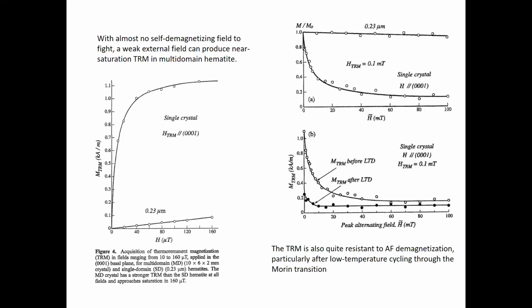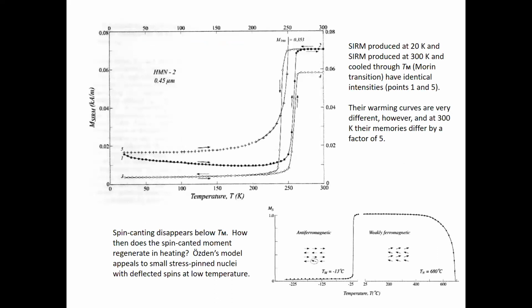And although the AF stability is not as large as single domain hematite, or else you wouldn't be able to demagnetize it at all, it's pretty respectable, and particularly after you've cycled through the Morin transition, which is the lowermost curve. This is more complex work. Özden got into a lot of experimental work about the memory of hematite's magnetism when you cycle through the Morin transition. And the real question here, since hematite at room temperature owes its magnetism just to a small canting of spins within the basal easy plane, and that completely disappears below the Morin transition when everything is pinned along the z-axis, and I do mean pinned.